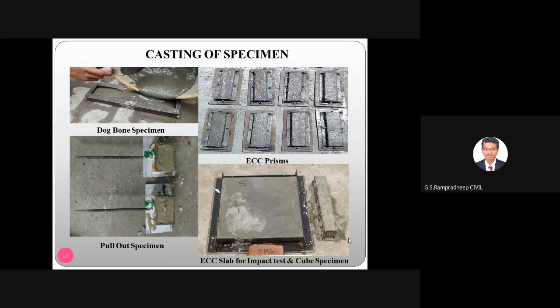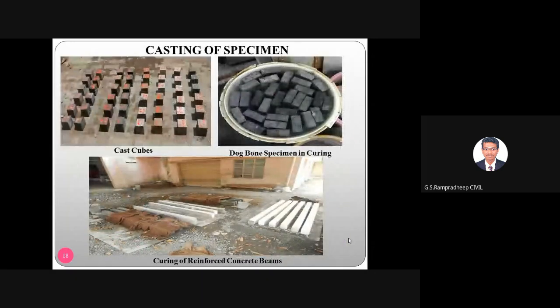So based on the ASTM C876 code of practice, you can get the potential, that is, how much percentage of concrete corrosion has happened. And if you see the last photo, it is for an ECC slab for the impact test and cube specimen, where he is using 60 centimeter cross 60 centimeter. This is a sample 7 centimeter cube he has cast, along with dog bone specimens. It is in curing, and the reinforced concrete beam is under testing. Actually, it is going for flexural analysis.